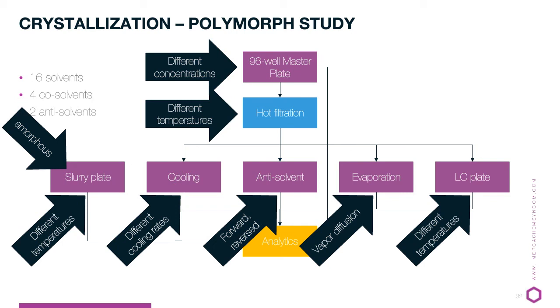In case of a cooling crystallization, in the lab you can have about any rate that is possible there to test. But in production, you are limited to the possible cooling rate of the reactor, which is most of the time much slower than you can achieve in a well plate. So looking at crash crystallization compared to slow cooling will give you the overview if you have a different form depending on your cooling rate. In case of an anti-solvent addition, you can use forward or reversed addition.